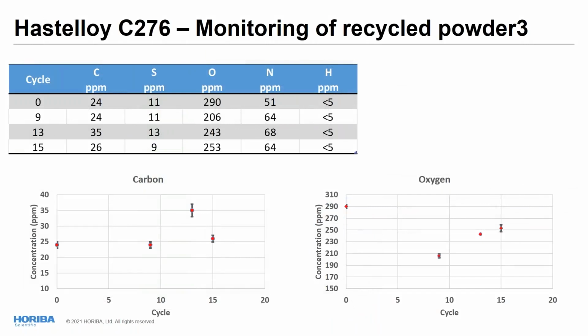powder. I see with a nice typo on the title of my slide. This was done on fresh alloy and after several cycles. The fresh alloy cycle 0 and also after 9, 13, and 15 cycles into the process. The results on the table were not showing any obvious contamination, and hydrogen remained undetected in all samples.